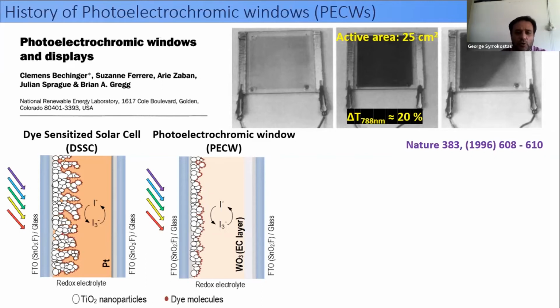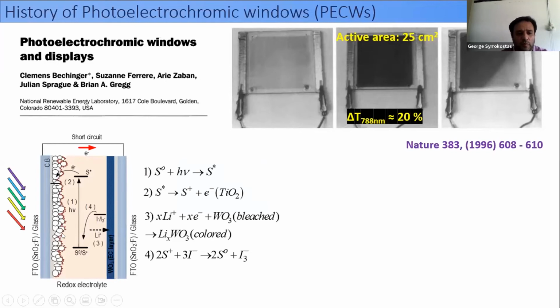In the case of the photoelectrochromic window proposed in Nature, at the anode we have a very thin transparent titanium dioxide film sensitized by an appropriate dye. Again, since the film is very thin, the amount of dye molecules that can be adsorbed on it are less. Therefore, the utilization of solar light is not so efficient. And moreover, at the cathode, the thin platinum film is missing, and we have the electrochromic layer. As a result, when photoelectrons are produced by the absorption of dye, when they reach the cathode through the external circuit, now they reduce the electrochromic layer, and due to the simultaneous intercalation of lithium ions, as we see here, the electrochromic layer changes its transmittance.